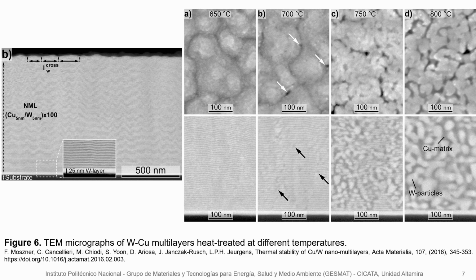One of them is the metallic nanomultilayer systems. In this case, metallic nanomultilayer systems of copper and tungsten have been investigated, with individual layers of copper and tungsten of different thicknesses in the nanometric range. For example, thermal degradation studies have been performed on these nanosystems to evaluate the operating window in future fusion reactors.